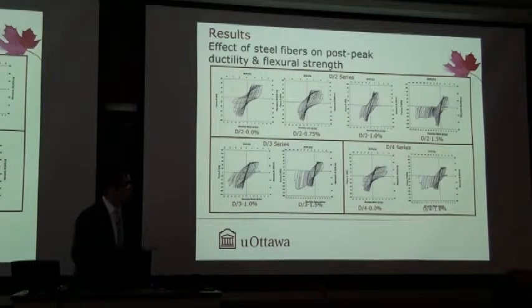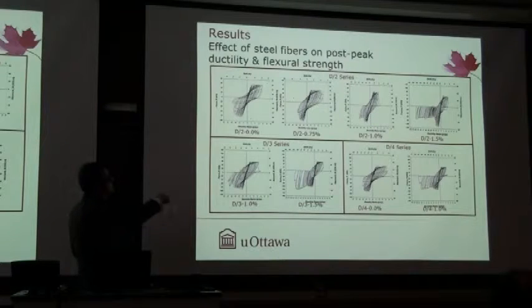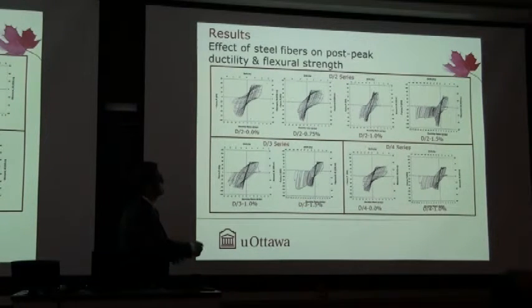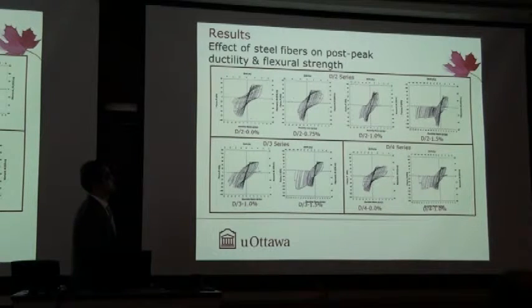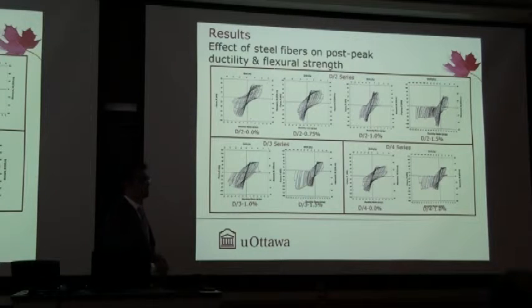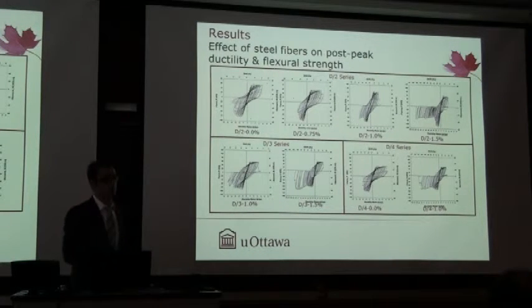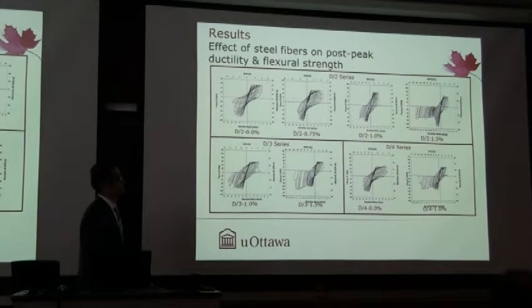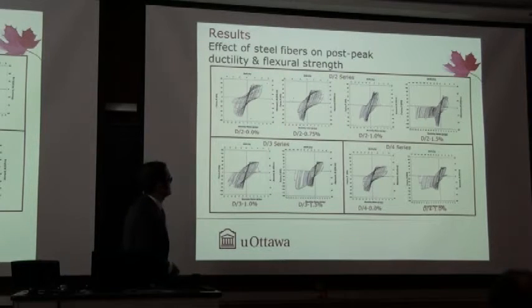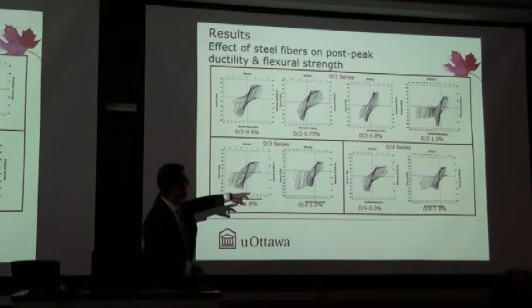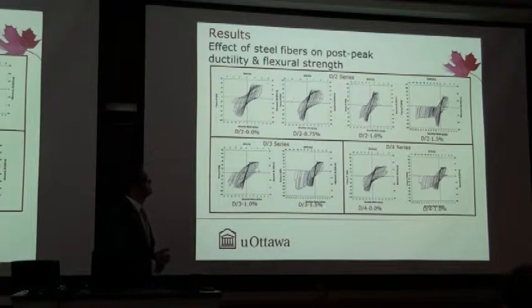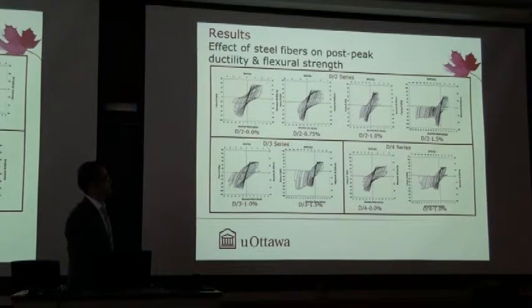These are the hysteresis curves, or load displacement curves, for all of my beams. At the top rectangle there, you can see my D/2 series with 0 to 1.5% fibers. If you look at the post-peak ductilities in the negative region, you can see a significant improvement in that area. In the positive region, we also had a little bit of improvement, but our number 15 reinforcement ruptured at an early stage, and that's why you're getting that unsymmetrical shape in our hysteresis curves. So we have different amounts of longitudinal reinforcement, positive and negative flexure. My D/3 series again showed significant improvement, also some strain hardening effect there. As well, in the D/4 series, we also observed significant improvement in post-peak ductility, and some strain hardening effect there.